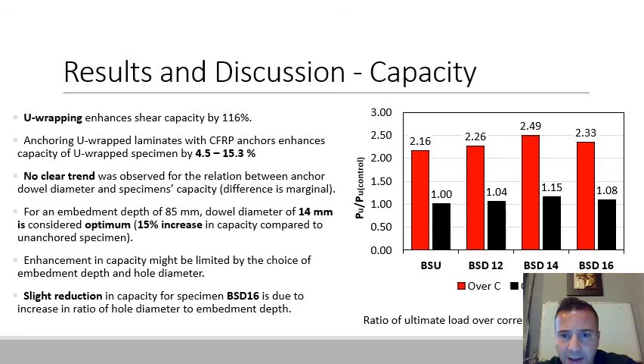Again, these are the results in terms of the loads, and we did not find a clear trend between the anchor dowel diameter and specimen capacity. The difference is marginal, and also we are using a relatively good value for the embedment depth, 85 millimeter, and the 14 millimeter diameter is considered optimum for this design. So enhancement in capacity might be limited by the choice of embedment depth and hole diameter. A slight reduction in capacity for specimen BSD16 is due to the increase in the ratio of the hole diameter to the embedment depth of the fiber, which was the same, 85. So basically you need more embedment depth to achieve the same capacity.